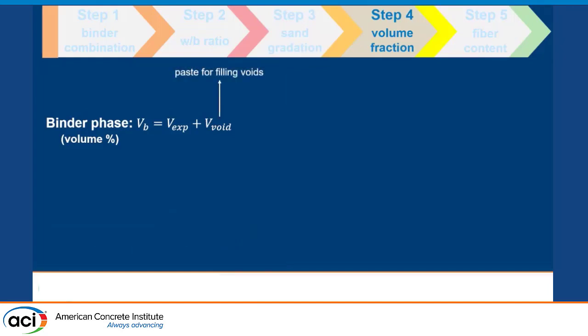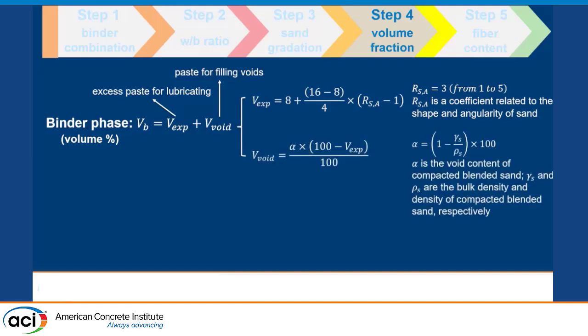So with the sand and binder ready, we can determine the volume fraction of each phase. For the binder phase, we can separate it into two parts. The V_void part accounts for the paste for filling the voids among the sand particles, while the V_exp part means the excess paste for lubricating. Here are the two equations for each term, and R_SA is a coefficient related to the shape and angularity of sand. Based on our visual observation, we determine it as 3. And here's the equation for the sand phase.